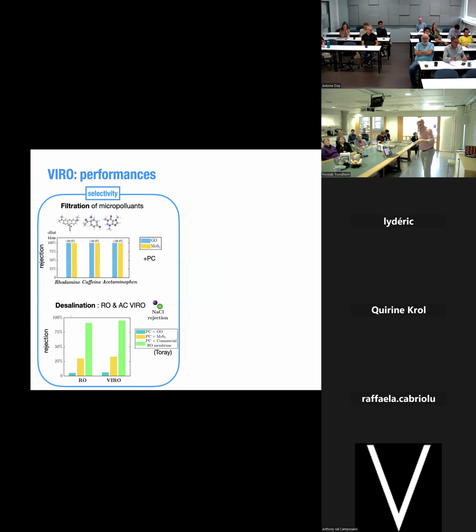And so what is the performance? First, very quickly, selectivity. Whether you put pressure or voltage, it's the same, of course, because it's the selective part which plays a role. For example, we played a lot with micropollutants, so hormones and things like that. For desalination, graphene oxide and MoS2 are bad, of course, because the size is 1 nanometer. They sieve the salt a bit, but not too much. But when you use a commercial membrane, the rejection reaches 100%. Just as for pressure driven, it works the same.